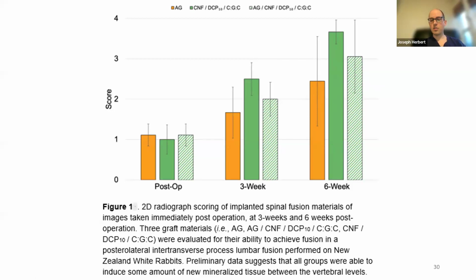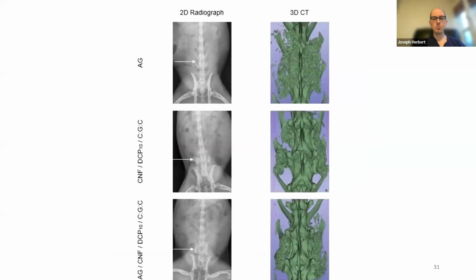These are very small sample sizes, of course. It's very expensive to do rabbit studies. And so there's probably no significant difference, but that in and of itself, to me, is a significant result, because we're taking this compound that's totally synthetic. The only aspect of it is that it's a biocompatible substance that's easily biodegradable, and it releases calcium and phosphate ions in a controlled fashion. And seemingly it's performing as good as allograft in this fusion model. We're basically putting plastic into these rabbits and causing a fusion.